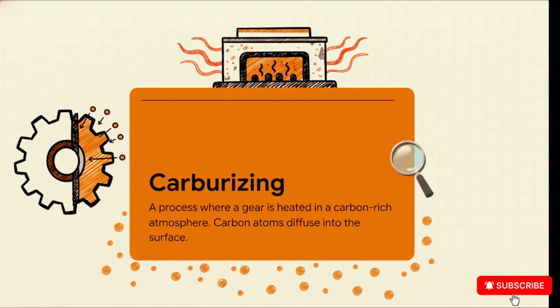Well, the most common method is a process called carburizing. You take the gear, you heat it up in a furnace that has this special carbon-rich atmosphere. And at those high temperatures, carbon atoms from the atmosphere literally soak into the surface of the steel. It's a process called diffusion. This completely changes the chemistry of the gear's outer layer. It basically turns it into high-carbon steel, which can get way harder than the low-carbon steel left in the core. And this is just a brilliant illustration of the result.